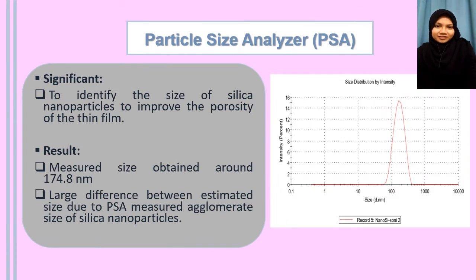Okay, for the third result, silica nanoparticle is characterized by using particle size analyzer. The significance of this test is to identify the size of silica nanoparticles that can improve the porosity of the thin film. So from the result, it can be seen that the measured size obtained is around 174.8 nanometer. There is a large difference from the estimated size of silica nanoparticles because PSA measures the agglomeration size of silica. To have a better analysis, silica nanoparticles can be characterized by using transmission electron microscope (TEM) in order to identify the single size of the silica nanoparticles.